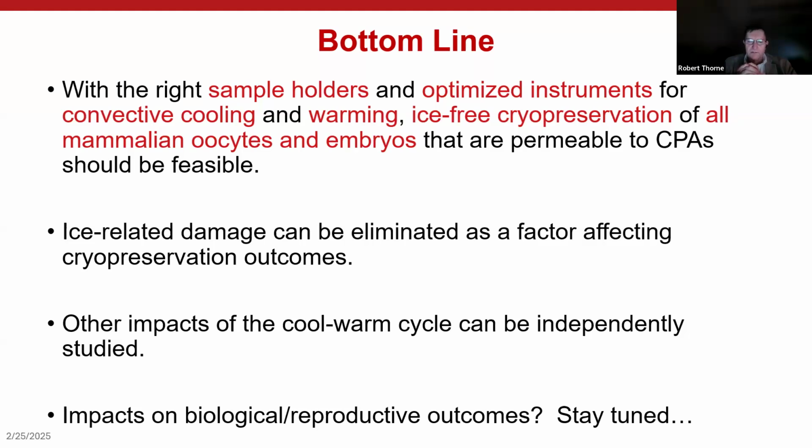So we tried to do some good measurements. What we found is boiling nitrogen versus ethane is about a factor of 11 in cooling rate. If we pump on the nitrogen to cool it to just above its melting temperature, that drops to a factor of 4. Pumped nitrogen is way easier to deal with than ethane, and that may be a good compromise.